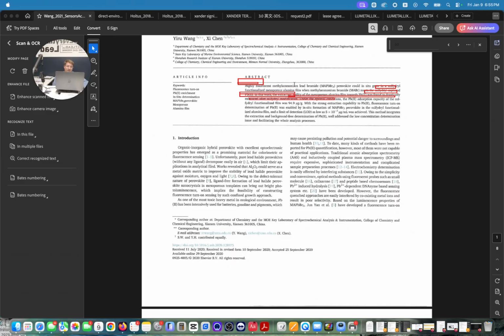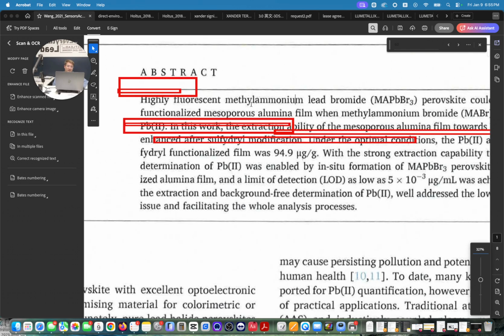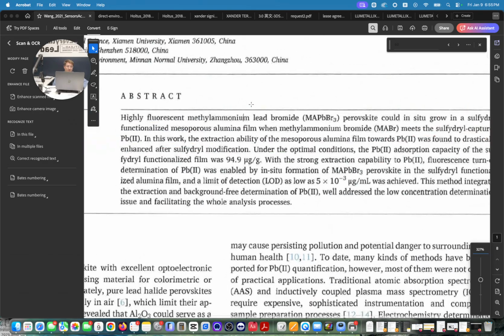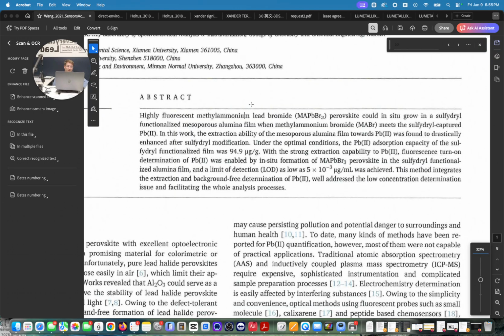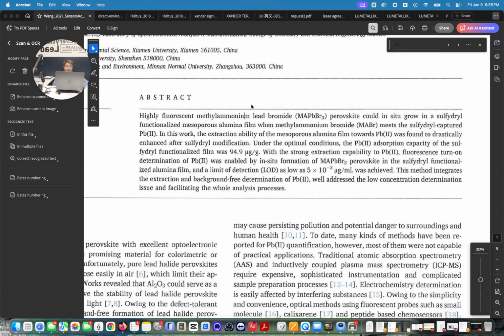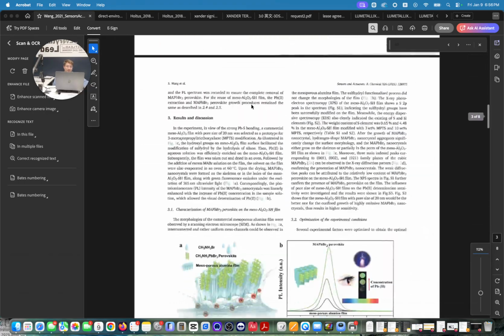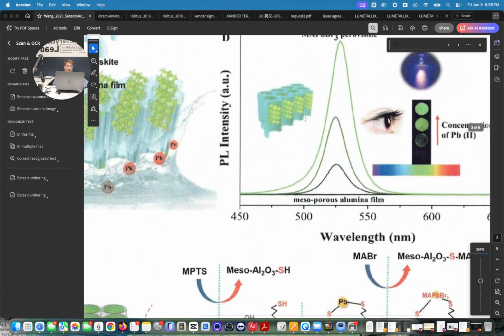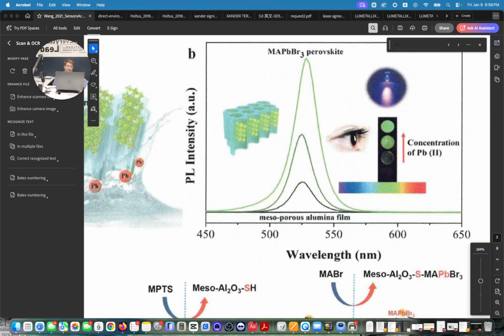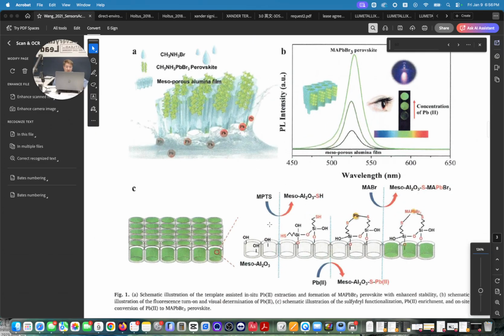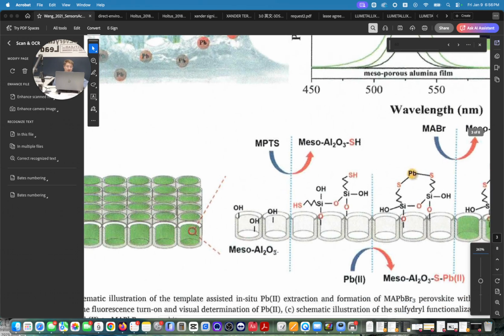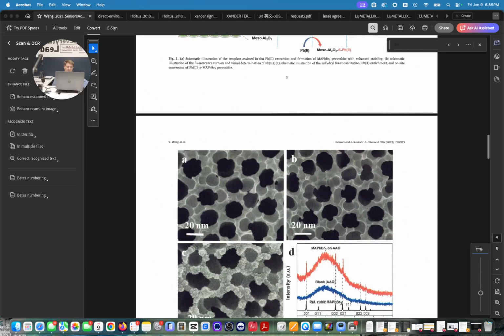So it says that highly fluorescent methylammonium lead bromide perovskite could in situ grow in a sulfhydryl functionalized mesoporous alumina film when methylammonium bromide meets the sulfhydryl captured lead, and that means that you can get a fluorescent compound. So you can see here that under UV illumination there's a glowing, and you can see that, right? And we can look at the steps where you have this mesoporous alumina, which is just tiny holes in the alumina. 20 nanometers is so small.